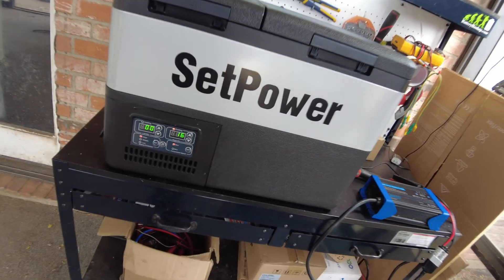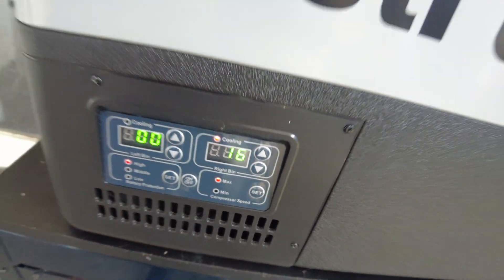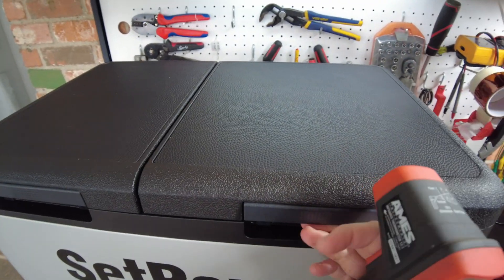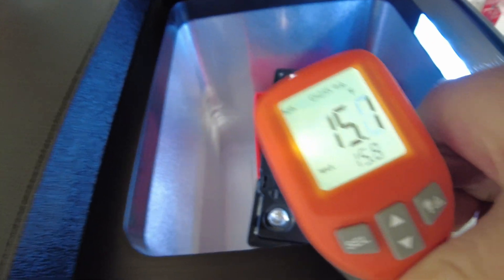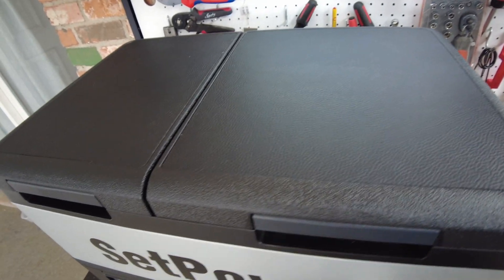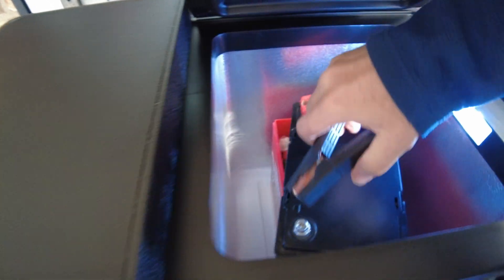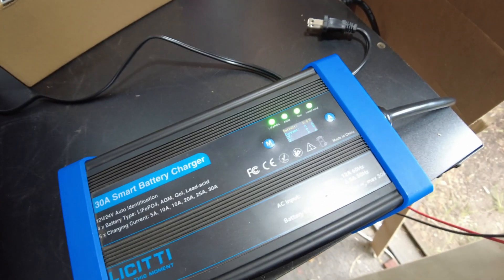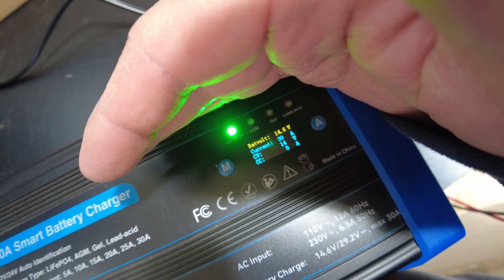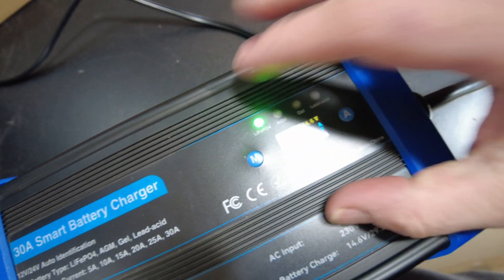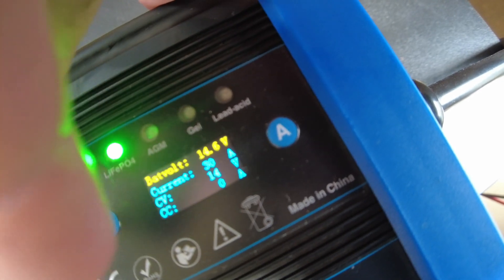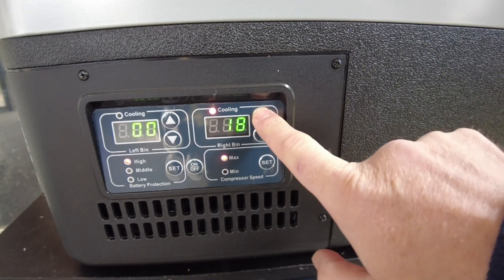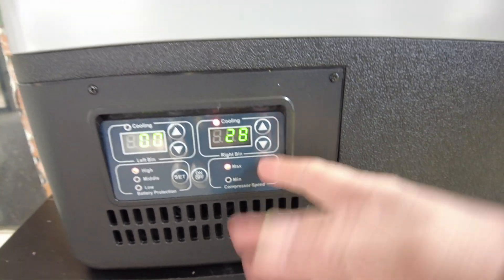Alright, so it's the next day, and we are showing 16 degrees Fahrenheit. Alright, let's take a look on the inside and see what it reads. We're showing about 15 on the battery. Let's connect it. And see if it'll charge. Alright, charger's plugged in. And again, not allowing it to charge, which is good. You can see there's zero amps going. So very good. So let's raise it up to, I don't know, 28 or something.